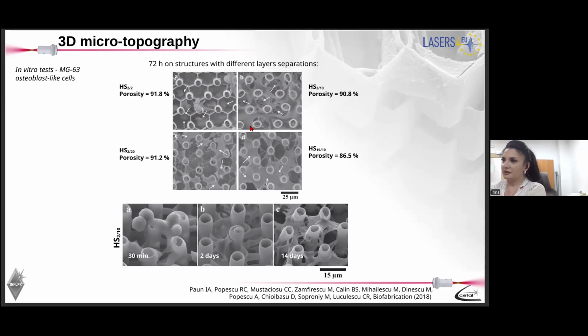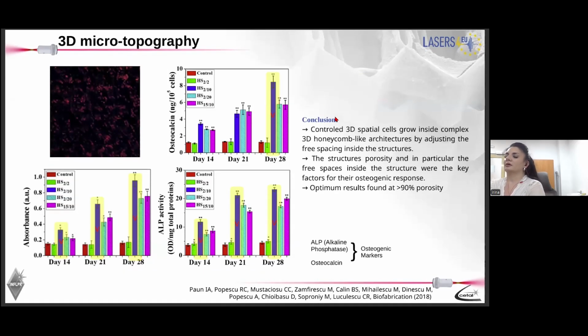Taking the best case scenario from here, this porosity, we monitored what happened with the cells from the early stage of cell seeding on the substrates towards later stages. You can see how they develop. They are here, they still divide, they start to attach, and then they start to penetrate inside the structures. The same as before, we made the same measurements on the osteogenic markers, and we saw indeed that the best structures in what concerns porosity are the ones with porosity more than 90%, which allow the fastest bone formation process.